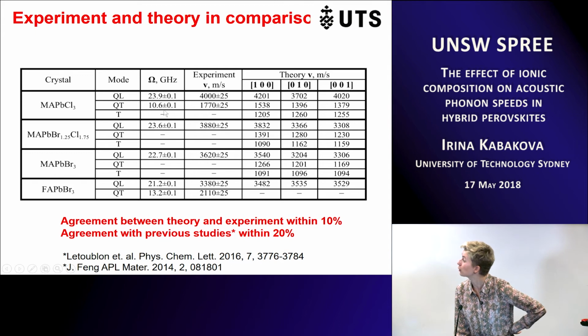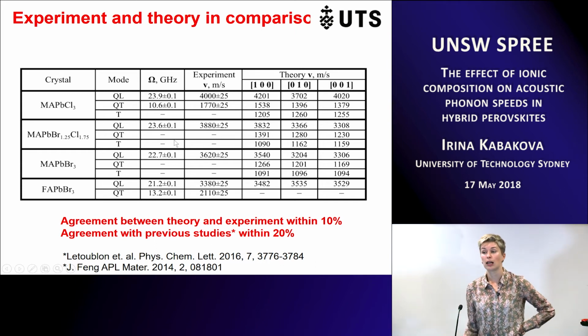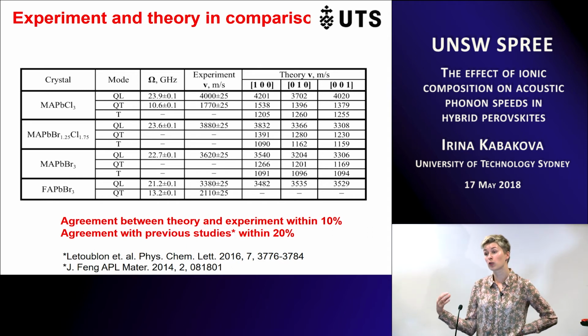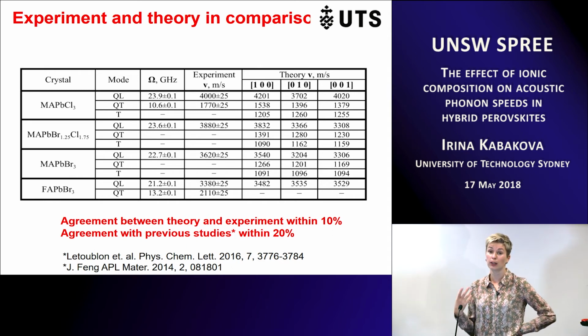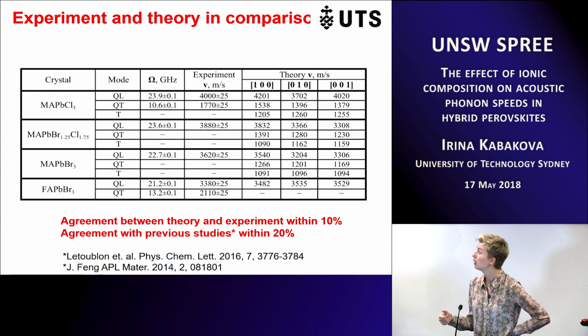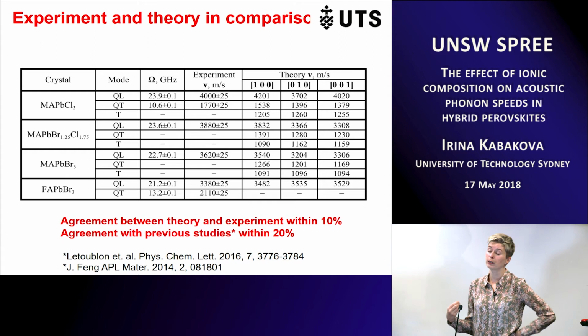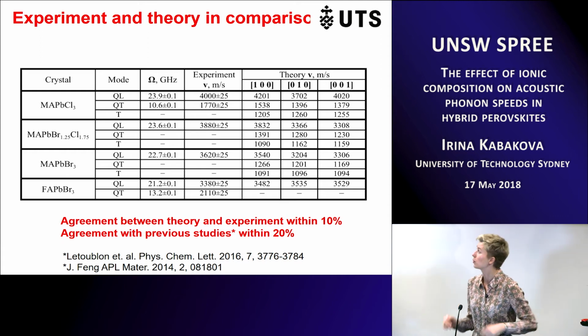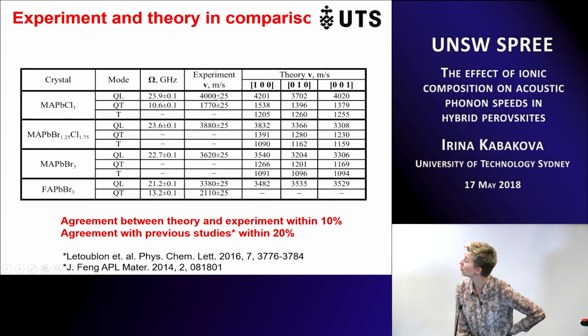And these are the frequencies that we've measured in Brillouin experiments. You see there are some missing fields here, and these were peaks which were too small to reliably fit and obtain a good measurement for, and they're usually for transverse waves, which do not couple very well in the scattering geometry. But nonetheless, we were able to obtain some speeds for longitudinal and transverse waves, for instance, for MA-lead chloride and FA-lead bromide. And these are the theory calculations.